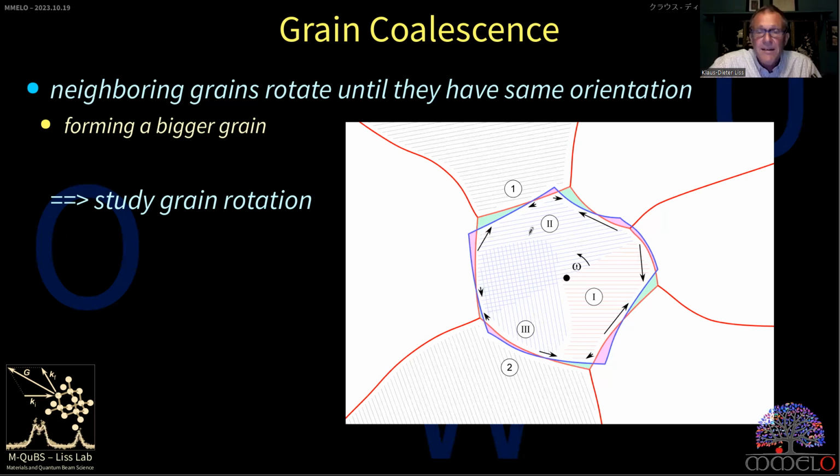So if the grain is like the nut and the matrix like the spanner, then the corners would prevent grain rotation or reorientation, unless I get mass transport. And we know at high temperatures we can have diffusion. Diffusion can transport mass. So we have these pink areas which have to be moved to the greenish areas by diffusion.